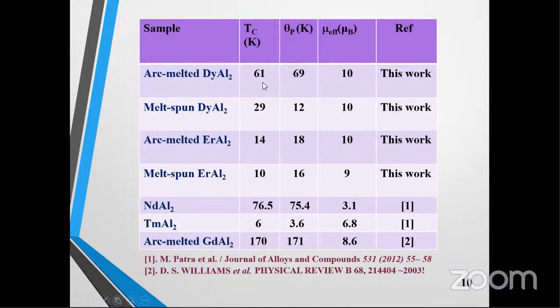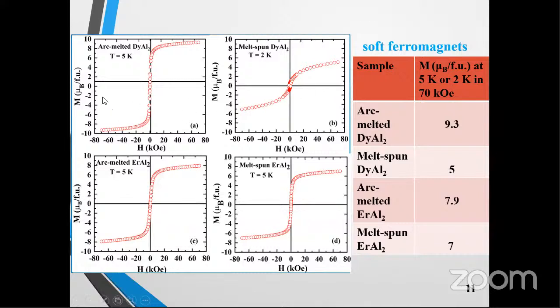This is 29 from 61 from both of the samples from their arc melted counterparts. So we can see that this is the proof of formation of nano grains, which has reduced the Curie temperature. And here we can see the magnetization versus field at 5 Kelvin, and it is for 2 Kelvin. Here we see that there is a negligible coercivity, which proves that these are soft ferromagnets. And I have listed the magnetization at 70 kilo field for these samples.